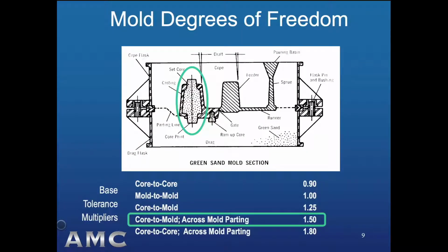The next most significant variable in the control of dimensional tolerances, but much more controllable, is mold degrees of freedom. In other words, freedom of movement in the assembly of the mold cavity. Most casting molds are assemblies of mold halves, cores, chills, and perhaps printed mold elements from additive manufacturing, but not all molds. Some are close to monolithic, most notably investment castings and sometimes die castings and lost foam castings. As we will see in an upcoming slide, even those mold cavity making processes can have degrees of freedom that affect dimensions, but not as much freedom relatively speaking.